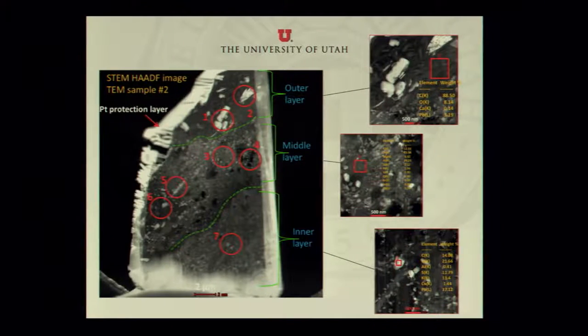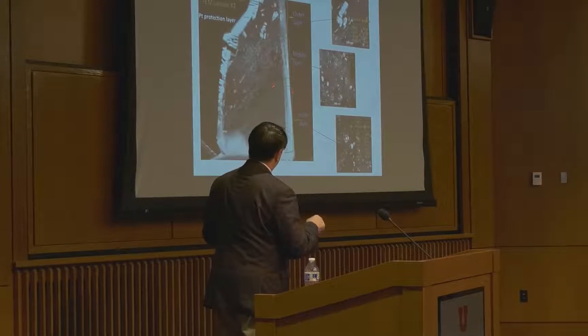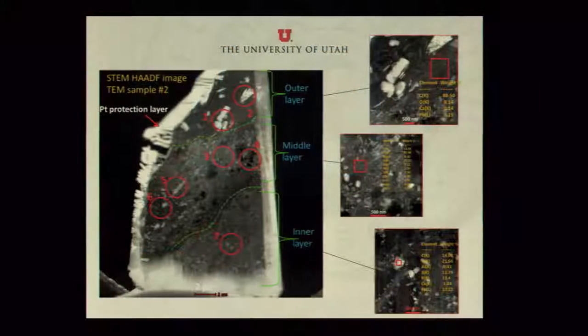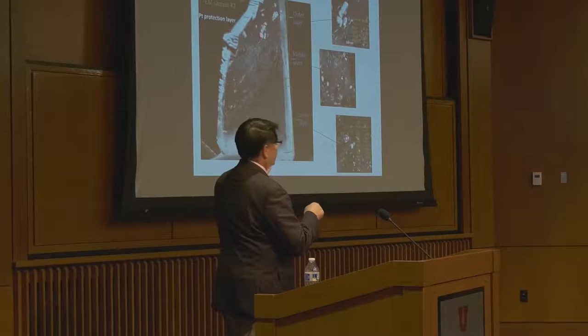This is a TEM cross-section of one of the areas of the pigment. If you look really closely there are three zones: down at the bottom there's fine microstructure — fine grains. In the middle the microstructure gets a little bit coarser — larger particles. As you go outward there are even larger particles. We discovered the composition also changes: going one direction you have more lead, going the other direction you have more sulfur. This particle size gradient suggests you might be observing some sort of nucleation and growth process — particles nucleating at the bottom and growing larger as you go outward.